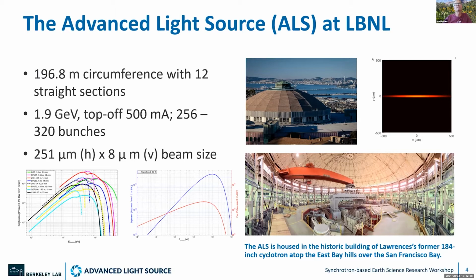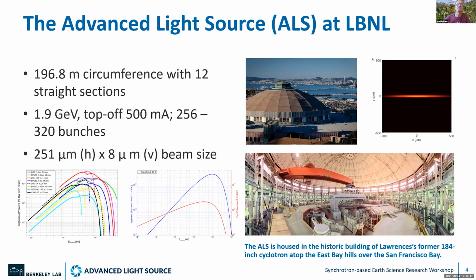The ALS underwent numerous upgrades in its 30-year history, and one of them, based on strong user demand, introduced three superbends. Those superbends, with between 4 and 5 Tesla field strength, have a critical energy around 12 keV, which pushes the useful flux and brightness into the hard X-ray range up to about 20 keV. Some beamlines even use up to 60 keV photons. These numerous upgrades also compressed the beam to the current size, with sigma sizes of about 250 microns by 8 microns. So it's much wider than it is high, which is the same as you've seen for the APS before.